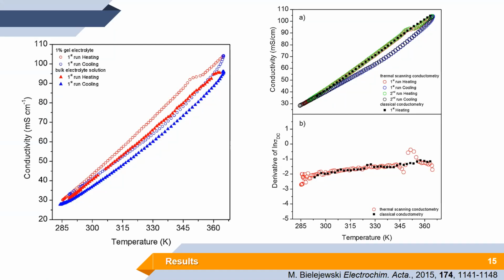And you can also notice some anomaly in that feature at high temperatures, which actually was recorded by the thermal scanning conductometry. And now just going into the future, I will tell you that it is connected with the phase transition when the internal structure of the gel network starts to dissolve. When we take a look at the right side of the slide and the upper feature, there are black squares, and these are the data obtained from standard conductometry. You can see that they are in perfect agreement with the thermal scanning conductometry, except the anomaly. And this is only because standard conductometry is not sensitive enough to record the phase transition when the system turns from solid to liquid.